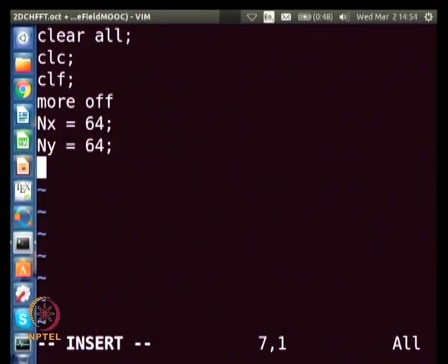So now we have to start an initial profile, and the initial profile is going to be a noisy profile. I am going to take some average composition, I am going to pick it as 0.5, because that is where the unstable region is, and I am going to put some small noise about 0.5, plus or minus some small noise. So let us do that.